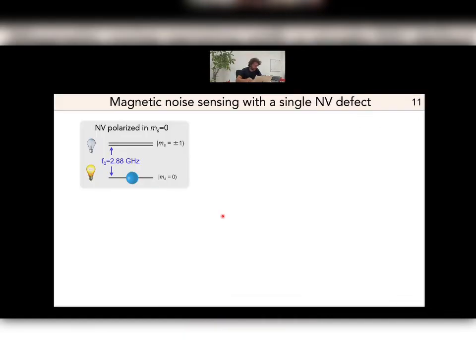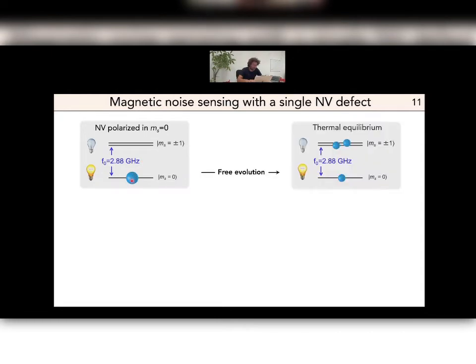So the first question we can wonder is how to measure magnetic noise with an NV defect. For that, I need to come back a bit on the photophysics of the NV defect in diamond. I just show here the spin triplet ground state. As a reminder, ms equals 0 is a bright state, and ms equals plus or minus 1 is a dark state. You can polarize the system by optical pumping into ms equals 0. So let's consider that the system is initialized in ms equals 0, all the population is there, and then we can let it evolve in the dark, a free evolution, to come back to its thermal equilibrium.